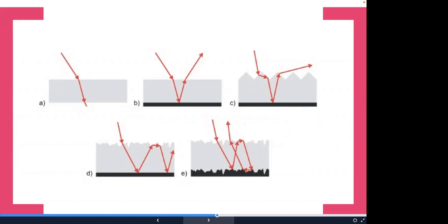I would say most of the most advanced solar cells do this with something called passivation, which is a way to get rid of these defects. Now, slightly older solar cells would actually use this texture because it was another way to get some amount of trapping, but still maintain a relatively good crystal structure, because this dimension here is much larger than the crystal lattice dimension. So it's always a trade-off. It's kind of an engineering trade-off.